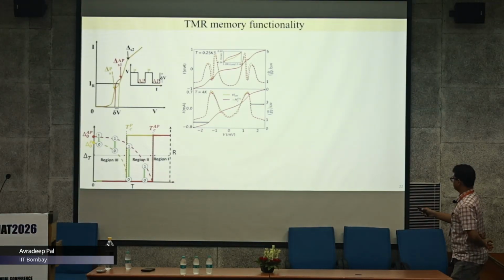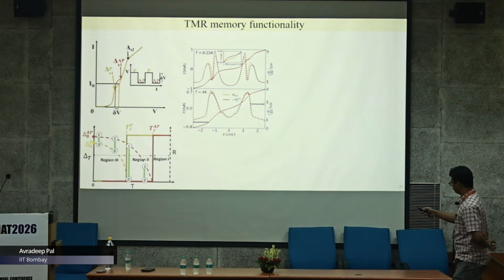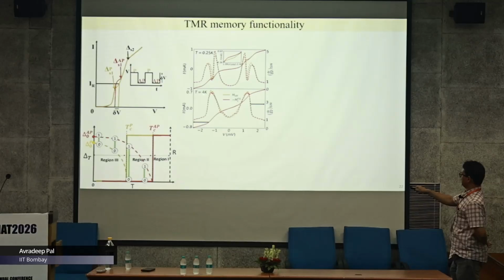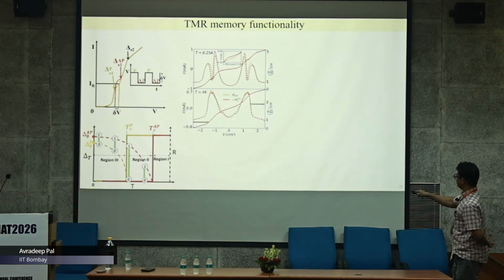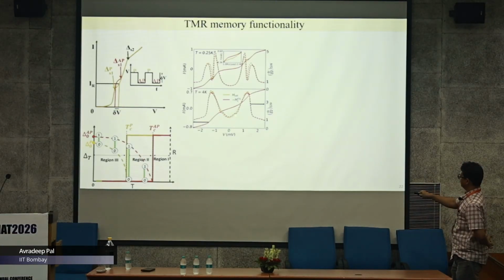At a temperature between the two TCs, that is 4K over here, remember, one was 3.8K and one was 4.2K. At 4K, you see the yellow curve here at a parallel field. There is no sign of any kink in this spectrum. But as I go into the antiparallel field, at minus HC of F1, the first layer switching, you see there is a kink that develops over here.